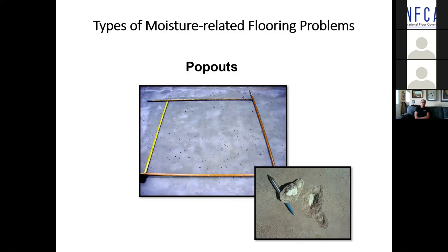What it turned out was that in this concrete mixture was an unacceptably high quantity, or percentage, of lignite particles. And lignite is a form of coal. They didn't do a good job of testing the moisture. When they covered the floor and the moisture redistributed and came up to the surface region, there was enough moisture to expand those lignite particles and actually cause deformity in the flooring.